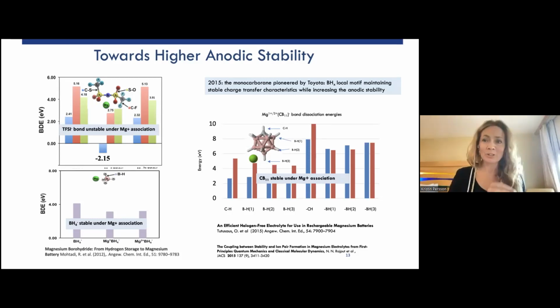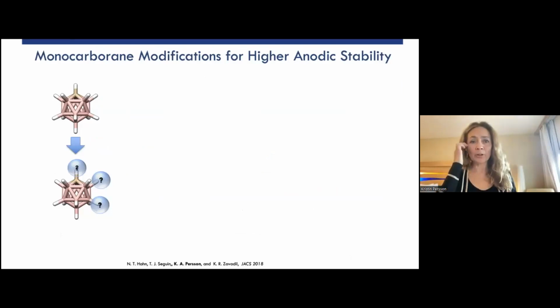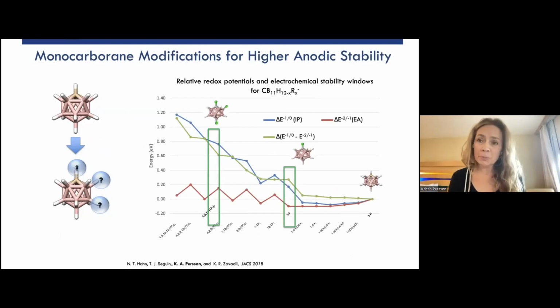So now we can go about trying to increase the anodic stability, or the electrochemical window, of some of these salts. We like the monocarborane, knowing that it works with magnesium metal. So we looked at the different parts that we could functionalize in the monocarborane, and different kinds of functional groups that we could add and substitute in. And then we can calculate how much of an improvement in the electrochemical window, an increase of anodic stability, we could gain from these functionalizations. And again, this is something that computation is quite good at. We just exchange the group. We don't have to synthesize anything. We can calculate it in the computer.